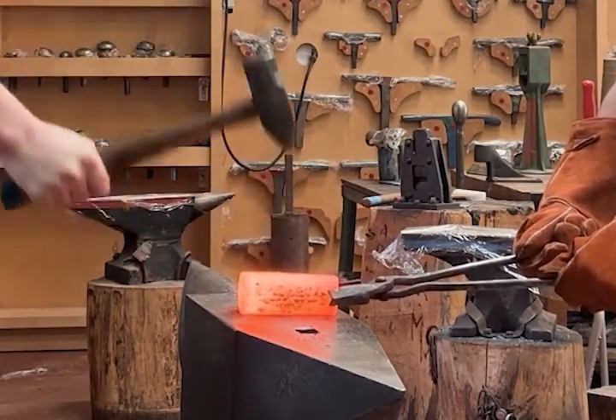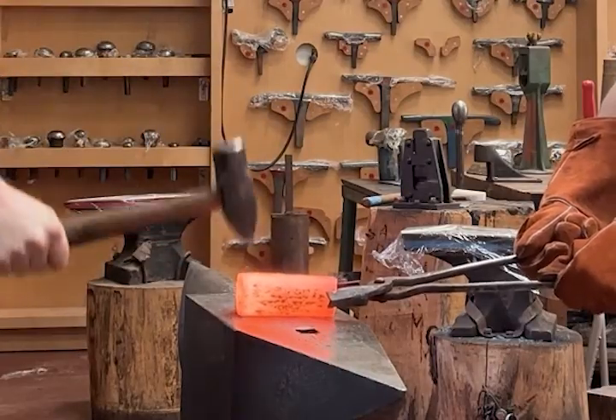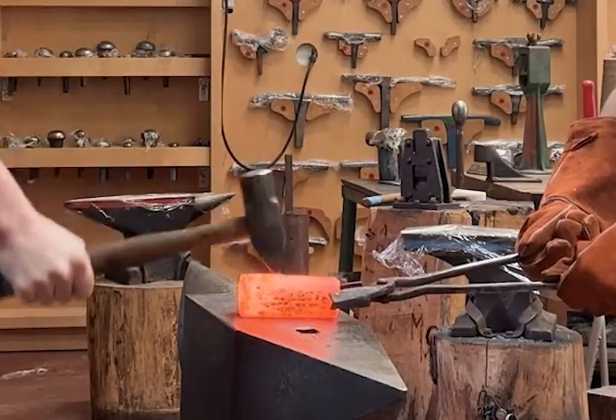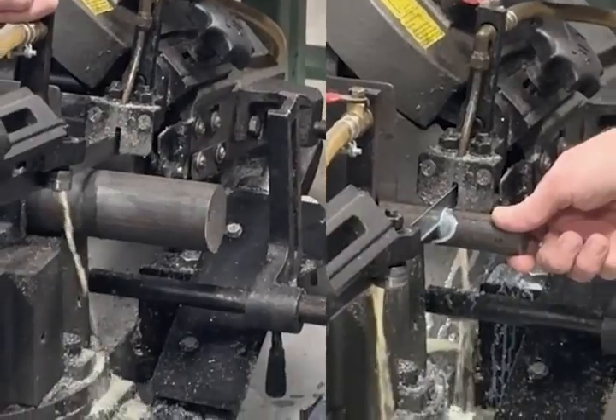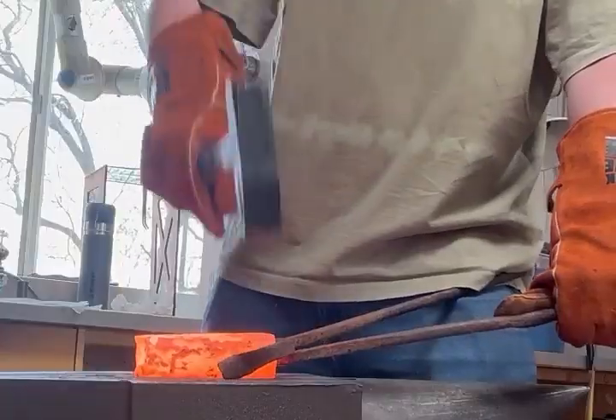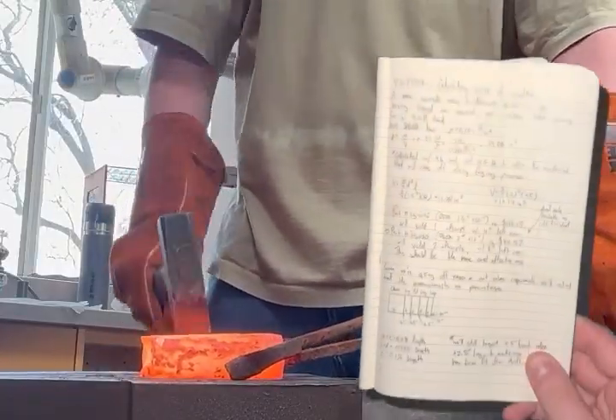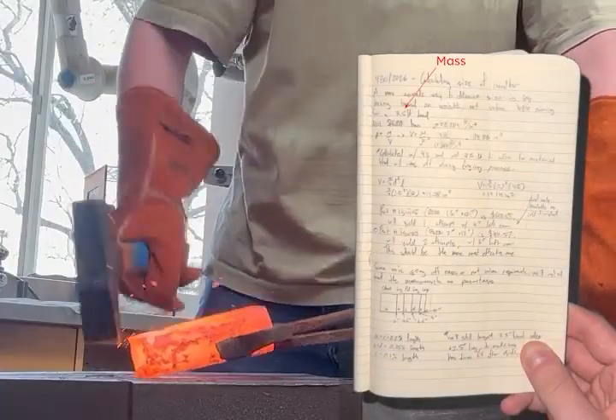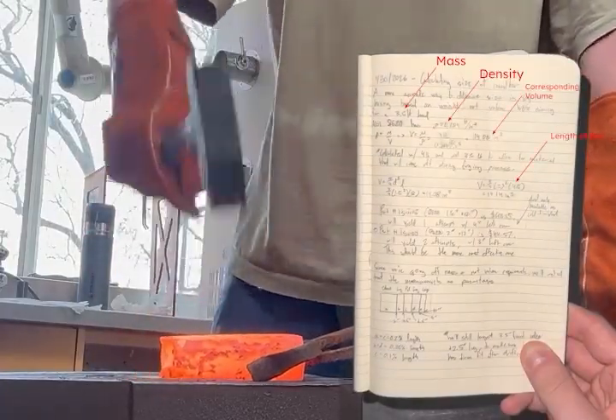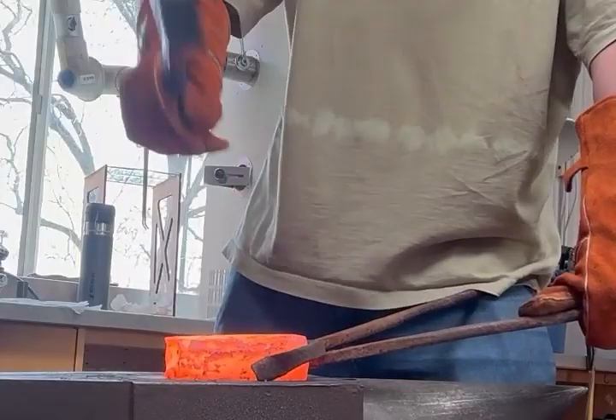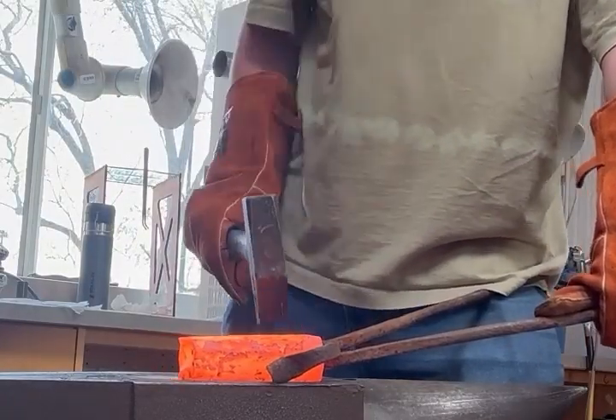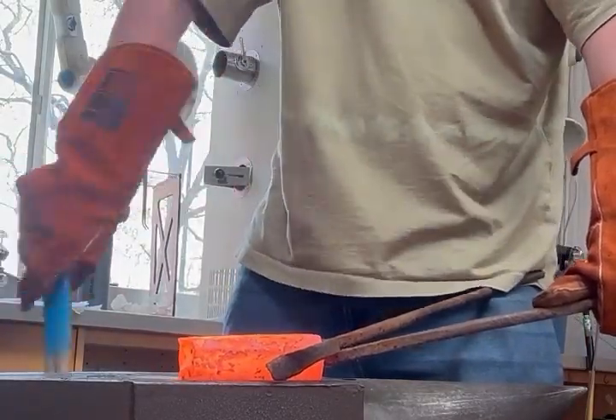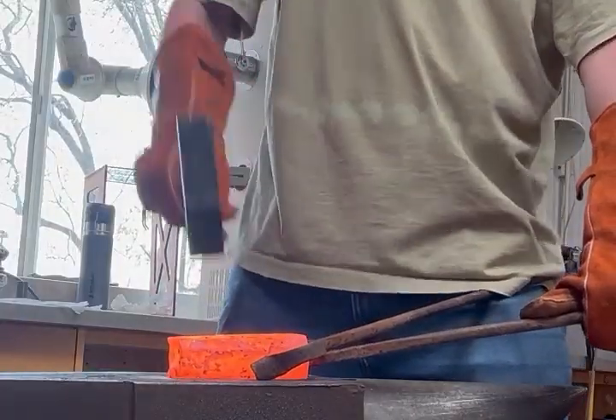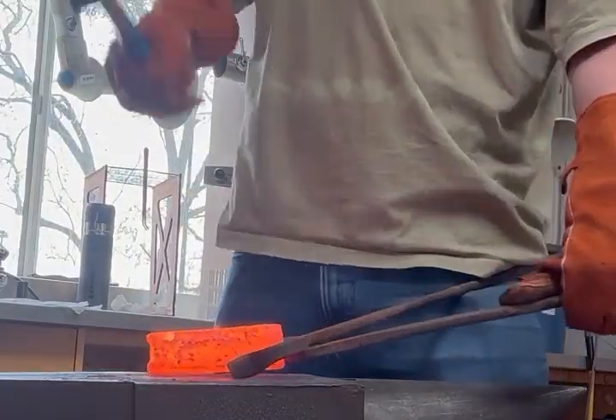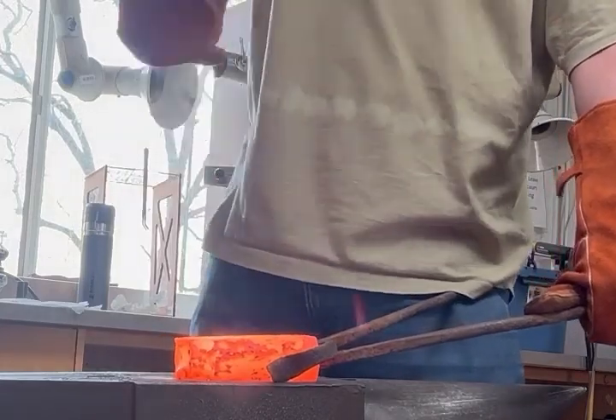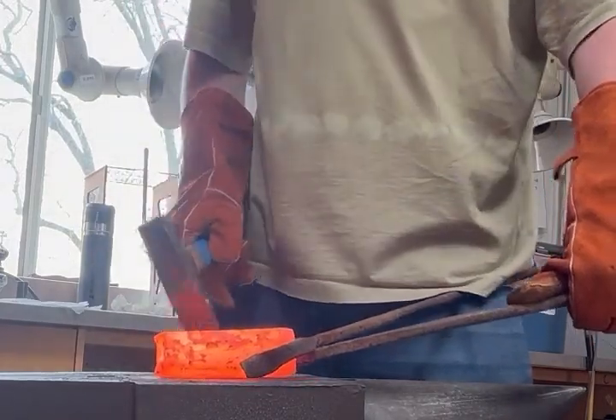Aiming for a 3.5 pound head, we started with 4.5 inches of 2-inch diameter steel bar after having both bars cut to length at our College of Engineering's machine shop. Variations to our initial plan began almost immediately. By selecting round bar, we were able to quickly determine the necessary volume for the desired mass, as well as to easily purchase our material as round bar was most abundantly available, but failed to consider that 2-inch thick metal would be resoundingly difficult to hammer out into a rectangle of about a 1/2 inch width, especially as we moved into this project with pretty minimal experience.